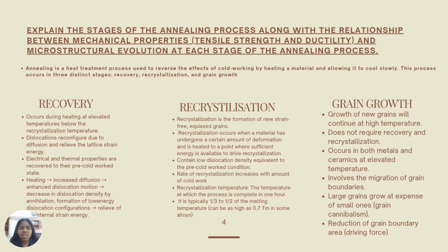The second stage is the recrystallization stage. It is the formation of new strain-free equiaxed grains. Recrystallization occurs when the material has undergone a certain amount of deformation. So the driving force is deformation. If no deformation has occurred in a material, then recrystallization won't occur. The grains here will contain low dislocation density, equivalent to the pre-cold-work condition, and the rate of recrystallization increases with the amount of cold work.